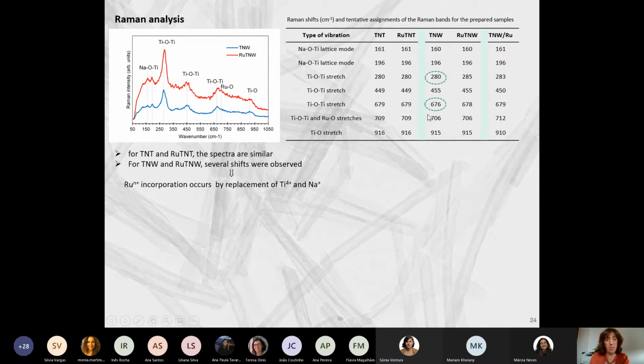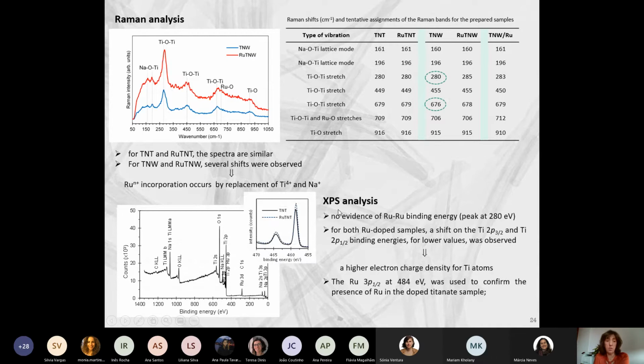And as you can see here, when we talk about titanate nanotubes, we have no changes in vibrations. But when we look at nanowires, we can see that the values are different. And if we compare these values with the sample that was prepared with the ruthenium only in the interlayers, this tells us that for this material we have some of the ruthenium in the interlayers. Of course, we need to confirm this by XPS, for instance, and as you can see here, these are the core spectra for the Ti 2p energies, and we have a small shift here.